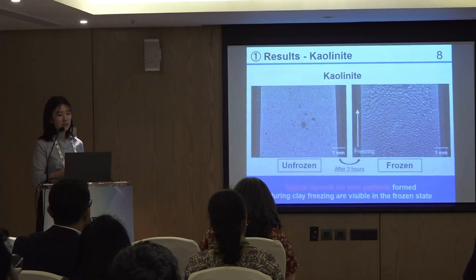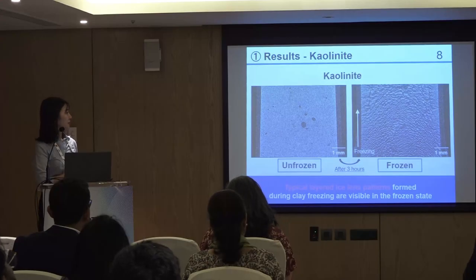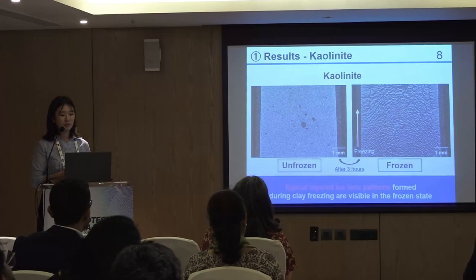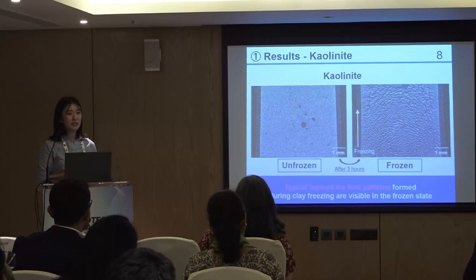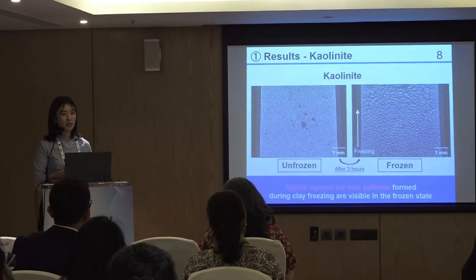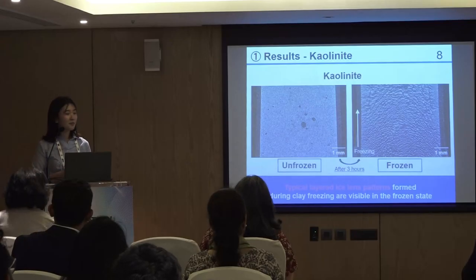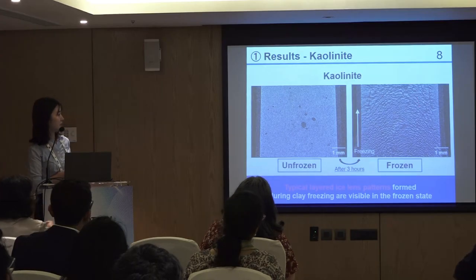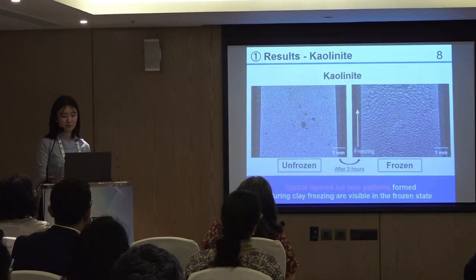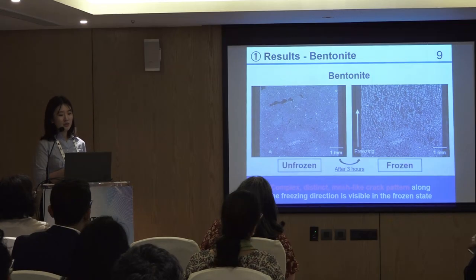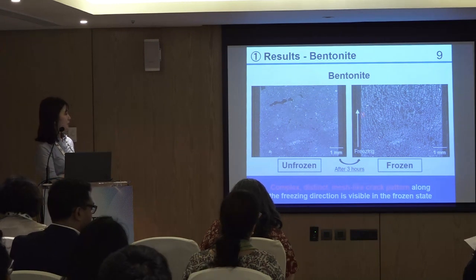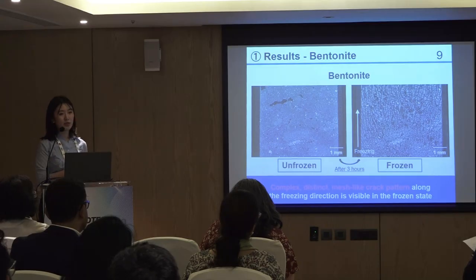Here are the CT scan results of kaolinite before and after freezing. In CT images, lower density areas show darker, so structures like ice lenses show up dark, while kaolinite shows bright. For kaolinite, we can see the typical layered ice lens pattern after freezing. Here are the results for bentonite. After freezing, bentonite showed complex mesh-like ice lenses along the vertical freezing direction, in contrast to the layered ice lens pattern observed in kaolinite.